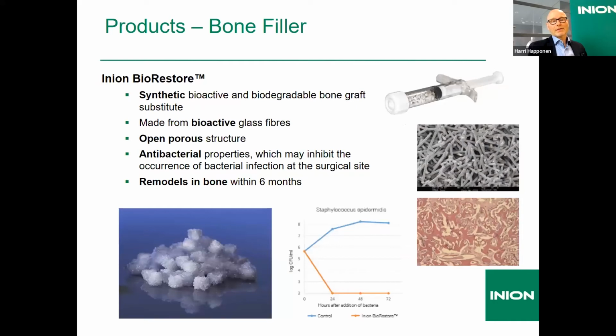And then finally, we have the BioRestore, which is the synthetic, bioactive and biodegradable bone graft substitute made out of bioactive glass. And it's made out of glass fibers, which are sintered together to form granules. And that allows open porous structure inside the granules here. So even though this looks like a sugar, they are all open porous, and there's around 70% of porosity inside the granules, which allows the bone growth inside the granules as well.